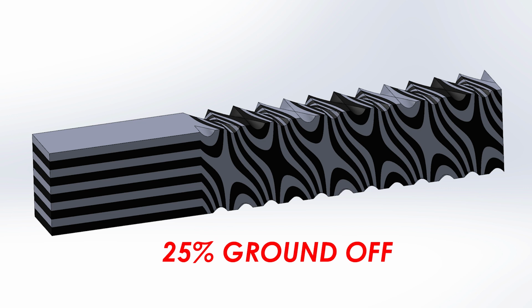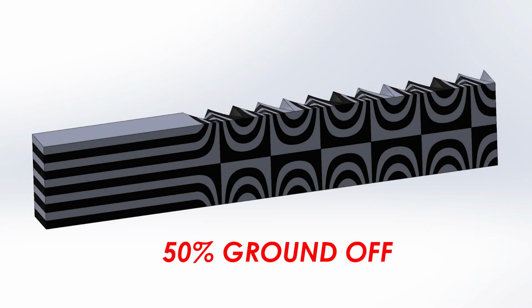This happens because it is easy enough to remove a bit too much off the surface when trying to create the right geometry in the final blade. Or it could have been because of trying to correct welding defects in the rods, and surely there could be other explanations. Notice that the slanting takes a backslash look when the billet has been twisted counterclockwise. This is also a familiar pattern that you can see in the original blade.